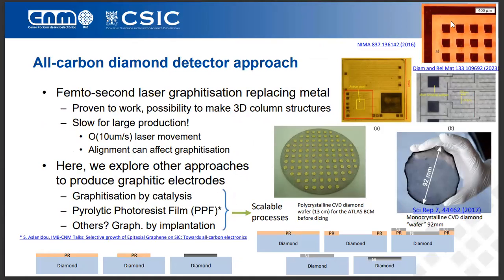This is also called the all carbon diamond detector approach. We're not the first ones to try this, but typically people use this femtosecond laser graphitization to replace the metal, which has been proven to work. And there's even the possibility to make 3D columns into the bulk out of graphite. The problem is that's slow. That's slow for large production.